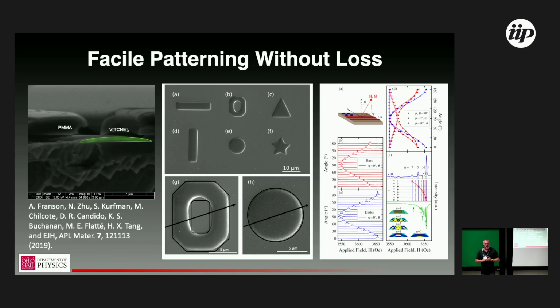Some combination of that and the fact that we're not etching and cutting sidewalls, introducing damage, means that when we make these patterns, and I'm realizing now I didn't put that data set in, but take my word for it, or you can check the reference, that introduces no additional damping. So this is unprecedented in magnetic materials. So not only can we get very low damping magnons, we can pattern them without any subsequent annealing or modification steps in a way that preserves that ultra low loss.